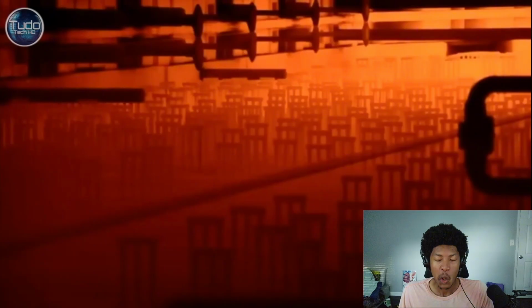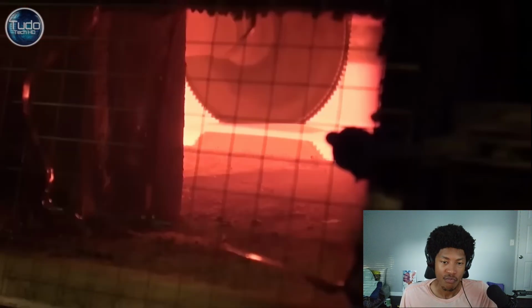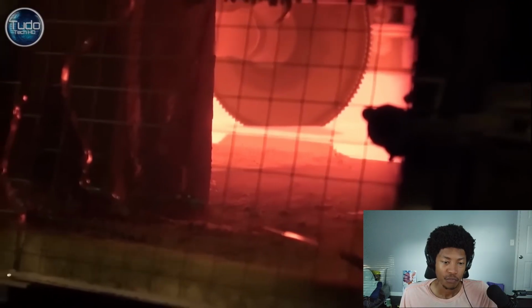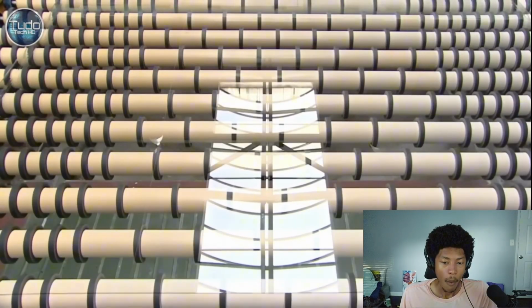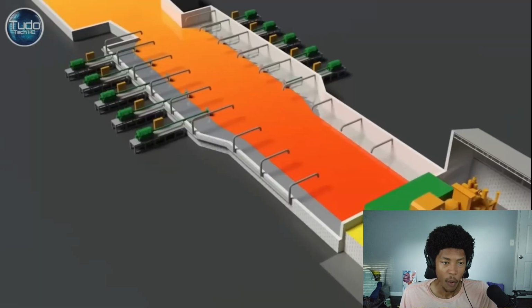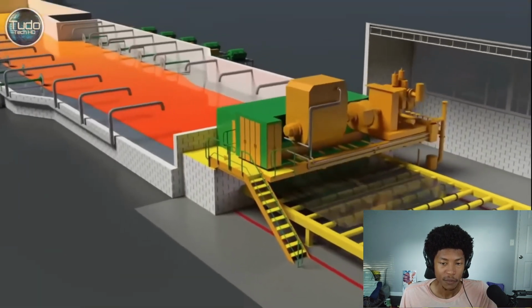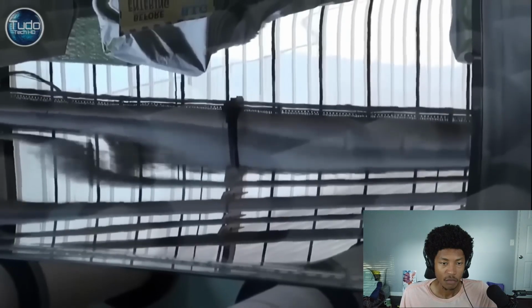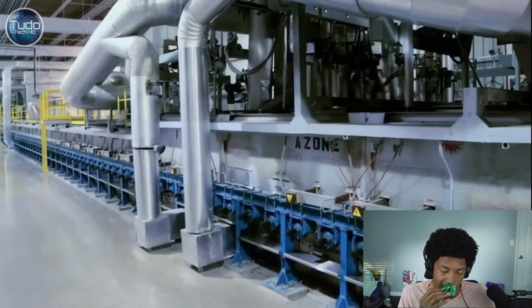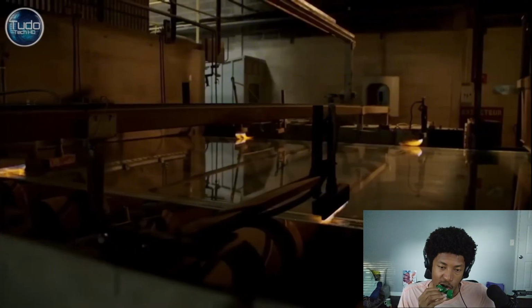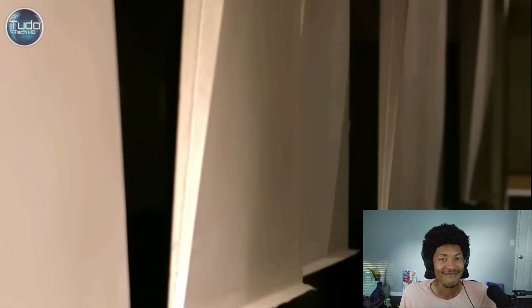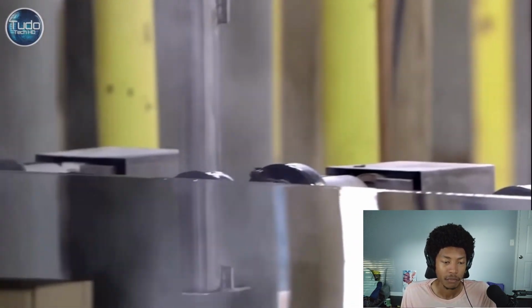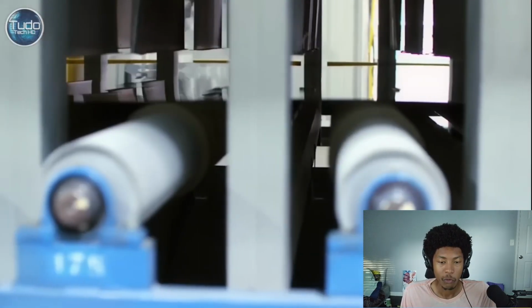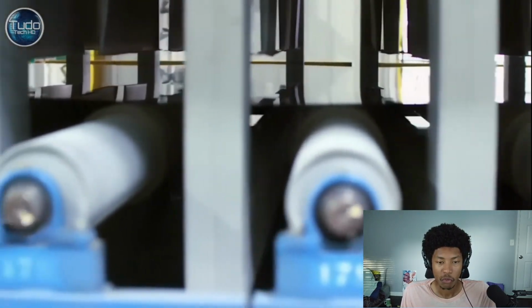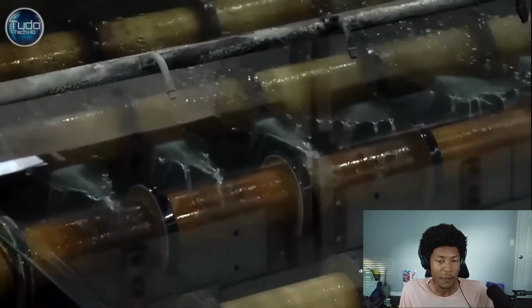Tin is a metal that remains liquid at high temperatures. It does not mix with the glass and provides a perfectly flat, polished surface. When it leaves the tin chamber, the glass is already solid, but still very hot. It then enters a special tunnel called a lehr, where it undergoes a gradual and controlled cooling process known as annealing. The glass enters the tunnel at approximately 600 degrees Celsius, passes through a slow and progressive cooling zone, and emerges at room temperature, completely stabilized.